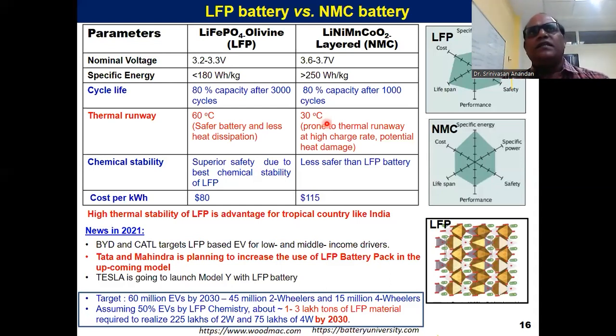So you have to select the cathode chemistry which is suitable for Indian climatic conditions. If you look at the thermal stability of LiFePO4, it is stable up to 60 degrees centigrade. So as far as we know, LFP chemistry is suitable for our Indian climatic conditions. If you want to use NMC, you can use it subject to providing a thermal management system. You should have a proper cooling system so that the temperature of the battery is maintained at room temperature. Again, it will add to the cost. Cost wise, it may not be competitive.